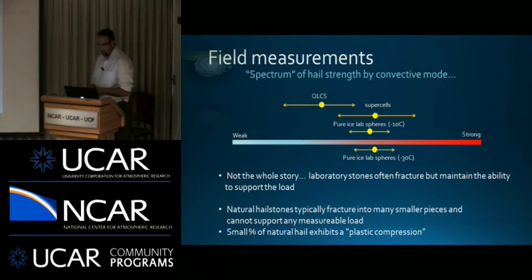And where does the spectrum of hail fall? And we can throw on the storm types, the QLCS and supercells. And I did that only because the QLCS, the only ones, we have 4 cases, were 30% weaker than pure ice. So, what about that environment is producing a very weak hailstone in a linear convective mode? And we barely have enough cases. I'm probably even hesitant to try to make that connection without more cases since our data set's dominated by supercells. But that was the one noticeable thing.